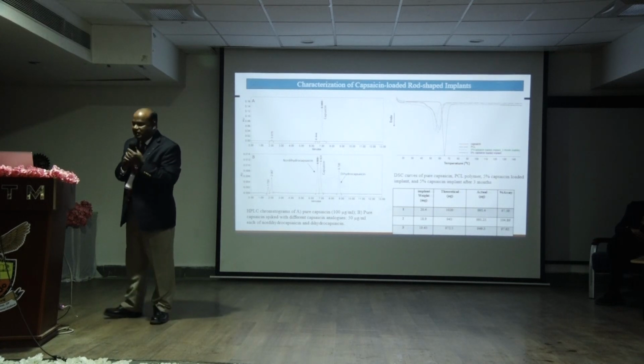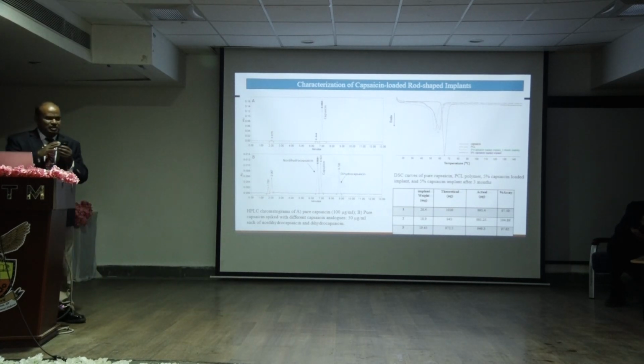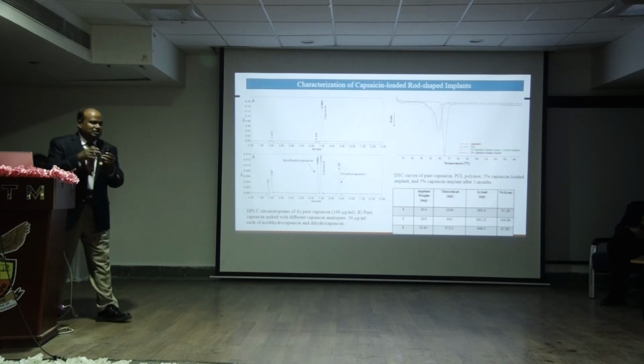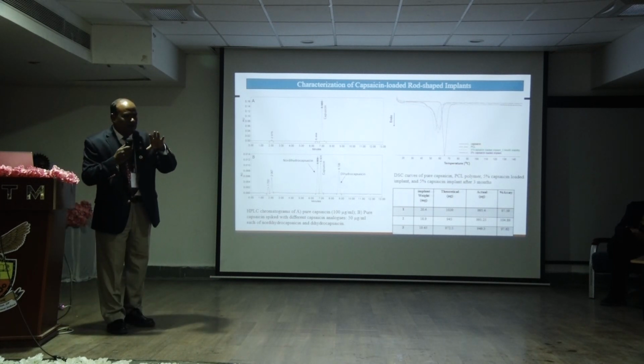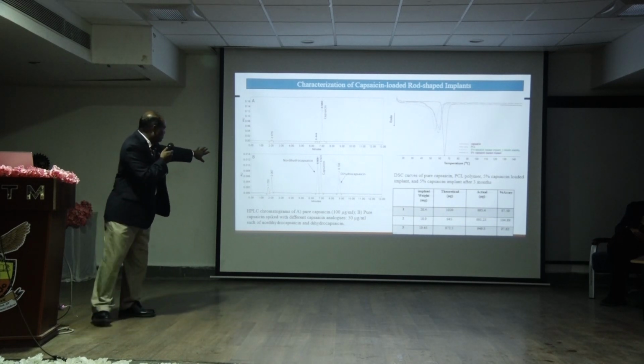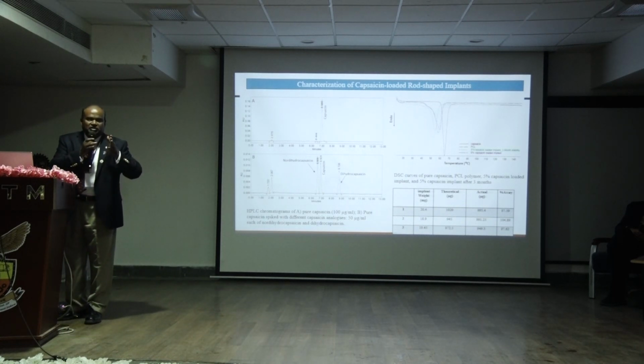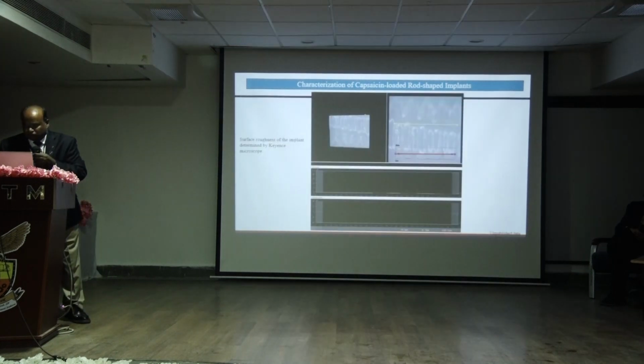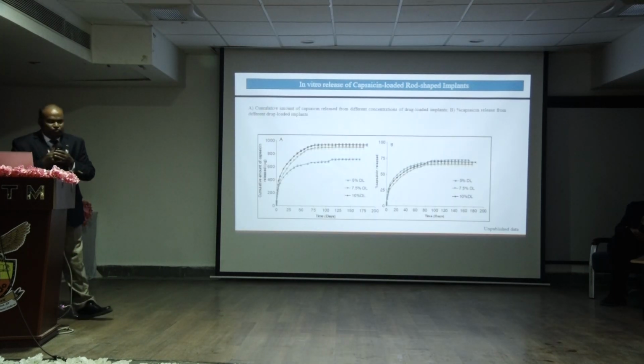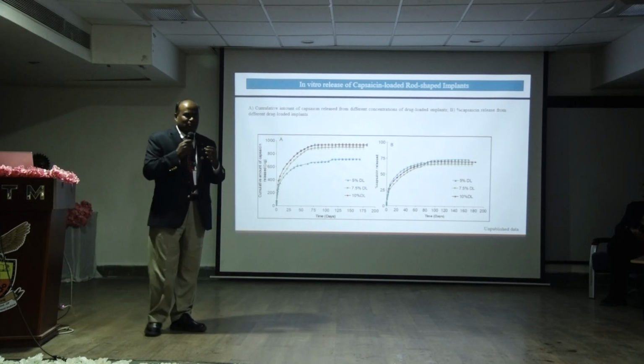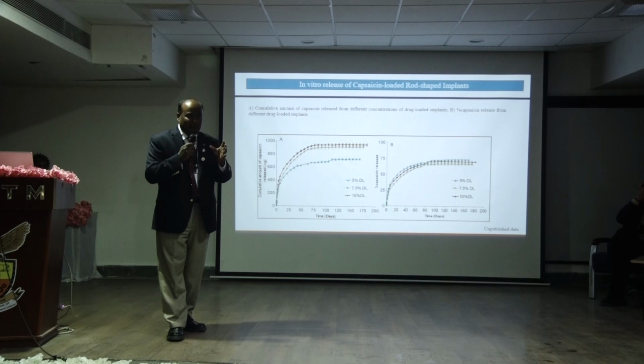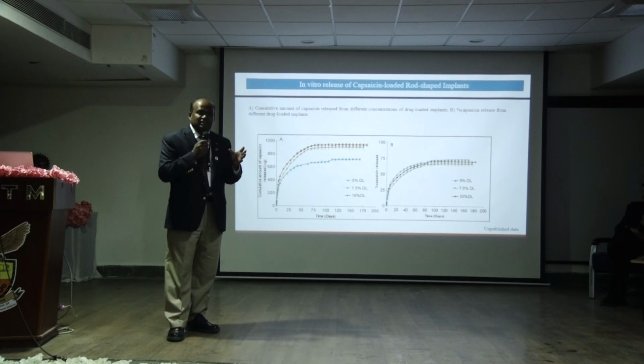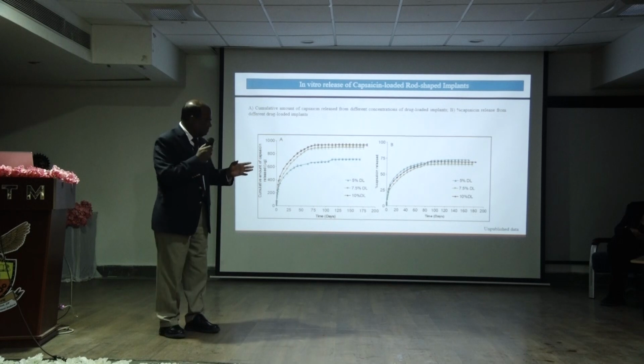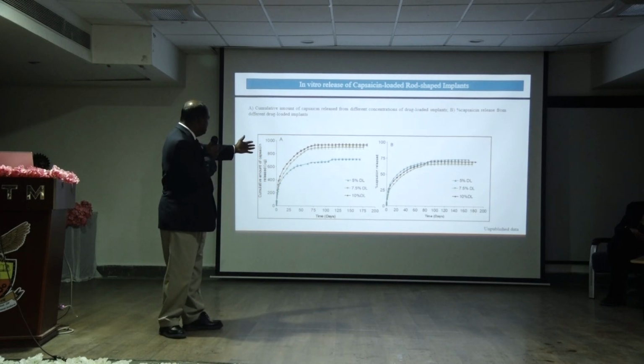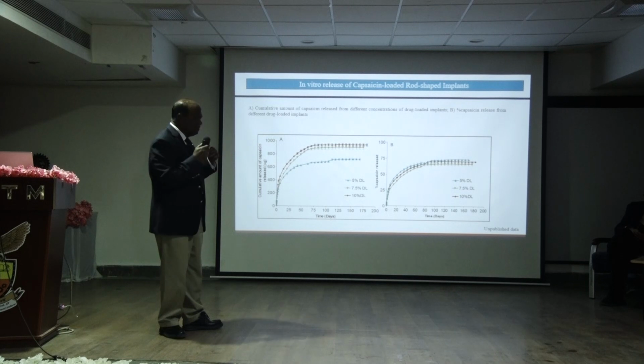And we also developed a capsaicin assay. Because we did the stability study, we had to show our assay method is stability indicating. Therefore, I'm showing that the method can resolve the degradation peaks from the main peak. So I'll skip this. We are able to develop a capsaicin delivery system by 3D printer, which has been releasing capsaicin for up to 6 months. Even at 180 days, still 75% of the drug is released, and the drug is still there in the implants.